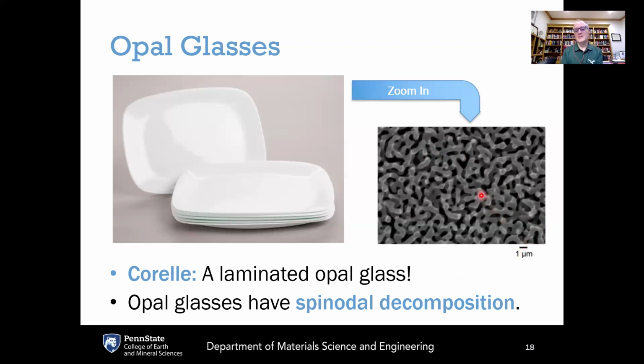And because the refractive indices of these two different phases are different, every time visible light tries to propagate through the system and encounters an interface, it's going to scatter at that interface. And that is what gives this the white color, so that all the light is being scattered at these interfaces. So this makes the interior part of these glass plates white.